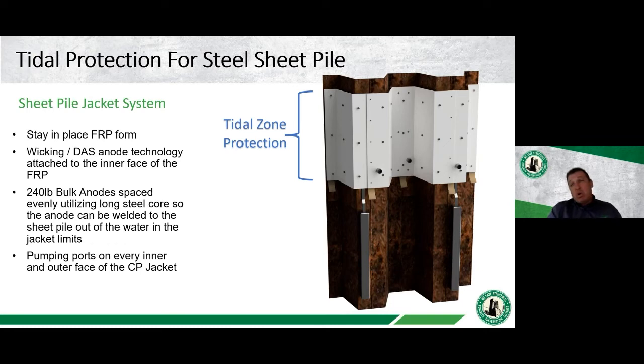What we have is the steel cores that are cast in the anodes. We have those steel cores extended up so that they can be welded to the sheet pile wall outside of the wet zone. So it makes it easier for the contractor to install. So we have the bulk anodes welded to the sheet pile wall within the jacket limits there. And then the jacket, either with the wicking technology or the distributed anode technology, is going to be placed in there. Now we're able to provide that galvanic protection to that tidal zone, which is also a very difficult place to protect. A lot of the times there's a concrete cap on top of this, so you can extend this jacket up to the bottom of that concrete cap on that sheet pile wall.